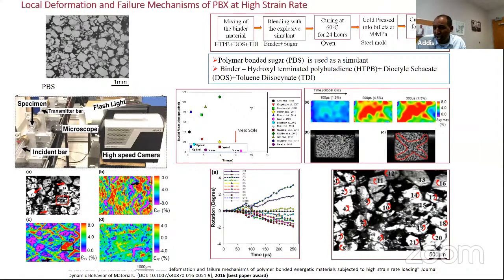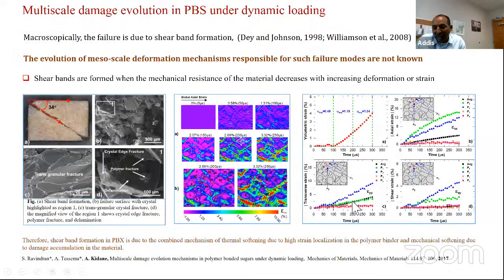We use polymer bonded sugar. Sugar is a crystal, and this is a specimen. We made it here at the University of South Carolina, and we tested at different loading conditions. Of course, we were able to measure the heterogeneity of the deformations, but what happens locally in these materials? One interesting thing we found, in addition to the local heterogeneous deformations, is that we were able to measure the rotation of the crystals inside this material, which actually changes how these materials behave under dynamic conditions. I will talk about this rotation in a minute and what it implies.